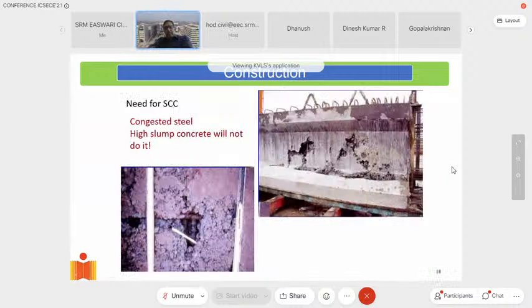So the little tangent here is that about 2 decades ago is when we started realizing that we need to get into this domain of rheology control. And the first few experiments were to look at this self-compacting concrete, or SCC. And the need for that came about because we were looking at placing concrete in reinforced concrete structures with very heavy steel congestion. And our conventional knowledge of concrete at that point of time was to make concrete more flowable by adding water. And the way we measured concrete flow was by conventional slump.